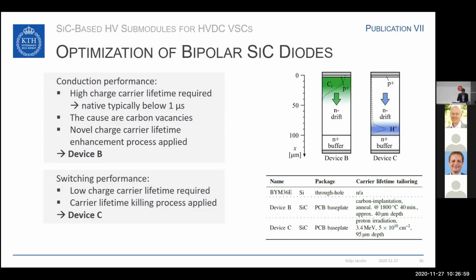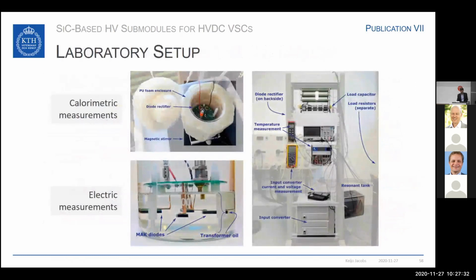What is also interesting to explain here is that for the conduction optimized device, two processes were happening during the lifetime enhancement. One was the carbon implantation on this side of the wafer. The other one was the thermal generation of new carbon vacancies in the rest of the wafer, which was done by the high temperature, in this case 1800 degrees Celsius. Therefore, we can expect that the lifetime is decreased in this region, but increased in the region close to the anode. We have built a laboratory setup in which we have done calorimetric and electric measurements.